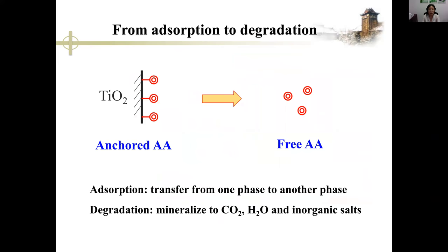After a series of factorial experiments with instrumental analysis, we proposed that the anchored AA in the TiO2 sol-gel played an important role in the photo-induced adsorption. Under UV radiation, the bond between the anchored AA and the TiO2 skeleton was broken, generating new adsorption sites for the dyes. After the UV light was off, because this structure is unstable, it rebounded again. This phenomenon is just like the water lily, which blooms in the day and closes at night. While studying photo-induced adsorption, we observed that sometimes the dyes could not be completely recovered — some were degraded during UV radiation. This led to the investigation of the UVAA process, turning the study from anchored AA to free AA.